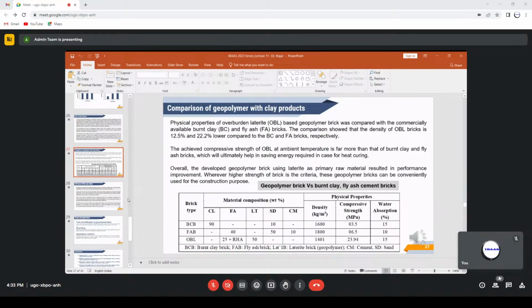Physical properties of overburden laterite-based geopolymer brick were compared with the commercially available burnt clay and fly ash bricks. The comparison showed that the density of OBL brick is 12.5% and 22.2% lower compared to burnt clay and fly ash bricks respectively. The achieved compressive strength of OBL at ambient temperature is far more than that of burnt clay and fly ash bricks, which will ultimately help in saving energy required in case of heat curing. Overall, the developed geopolymer brick using laterite as primary raw material resulted in performance improvement. Wherever higher strength of brick is a criterion, these geopolymer bricks can be conveniently used for construction purposes.